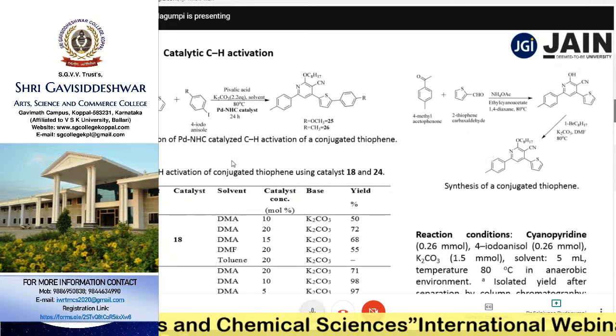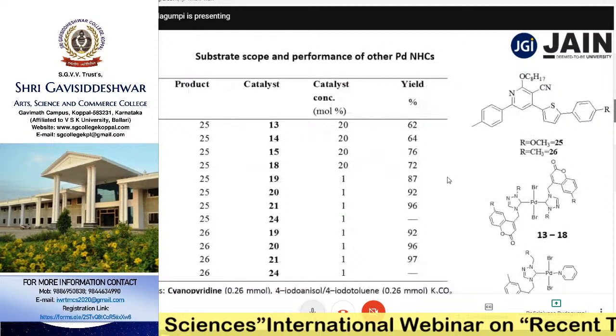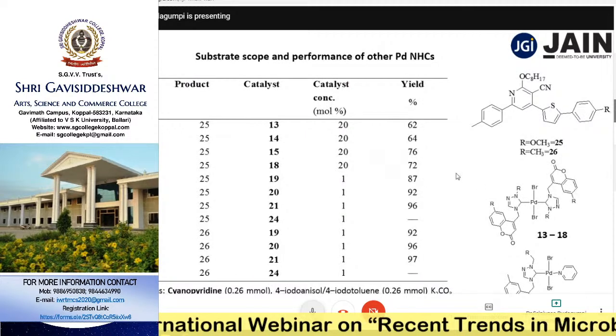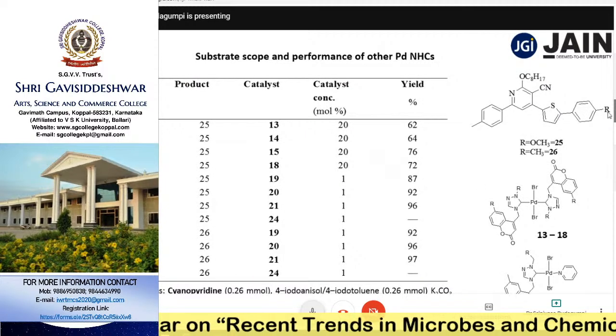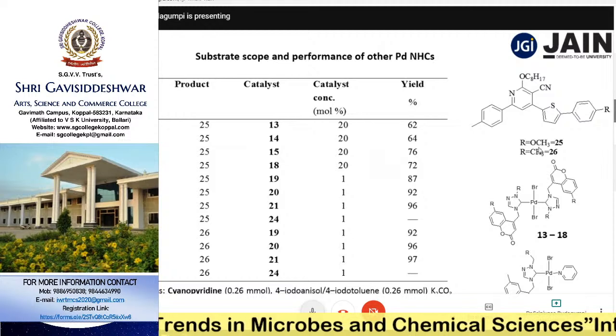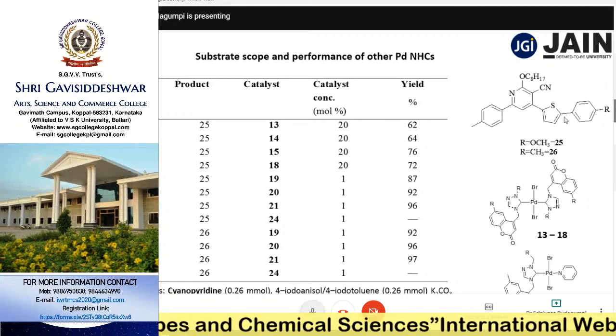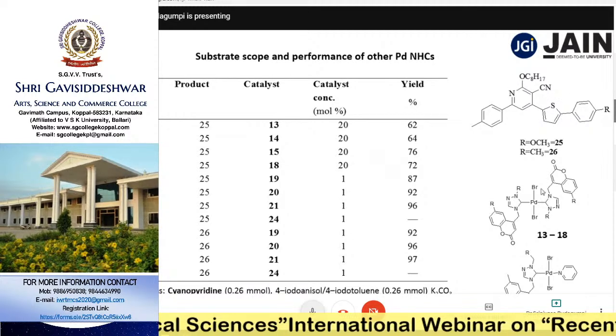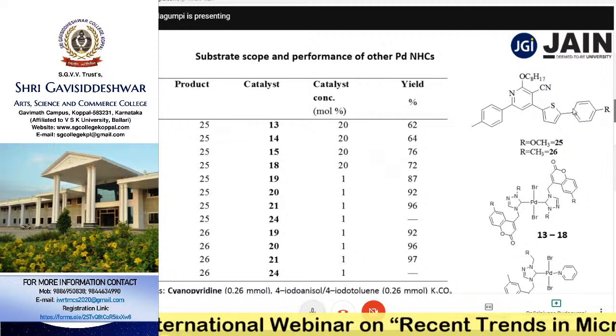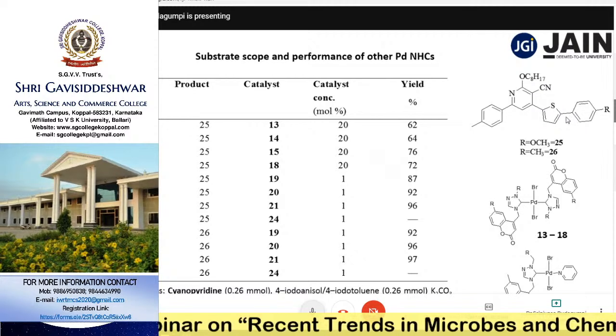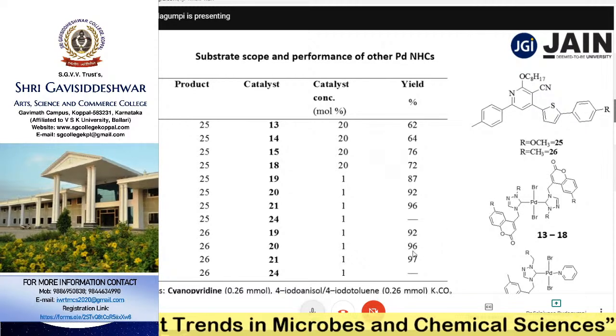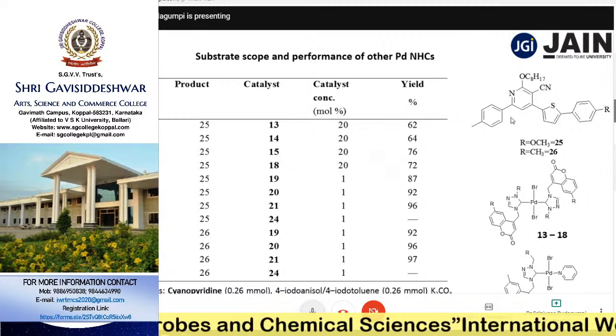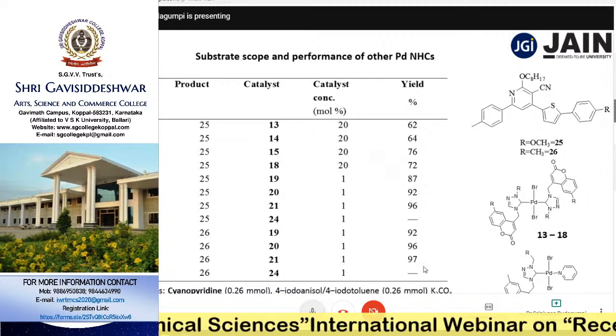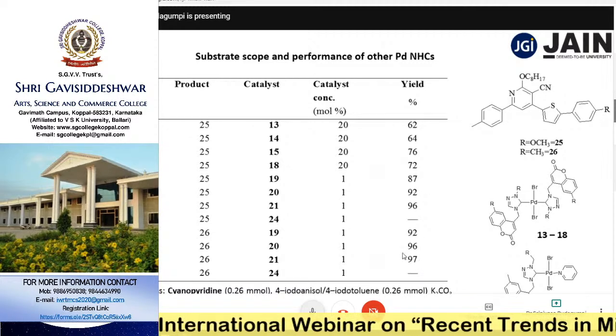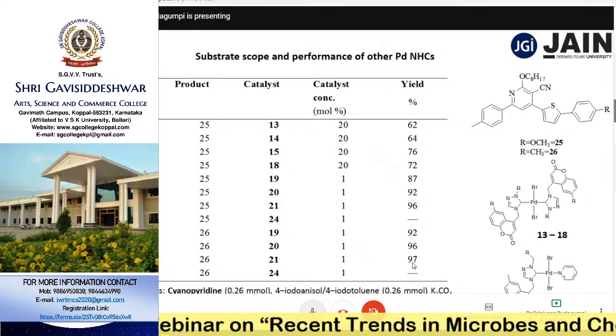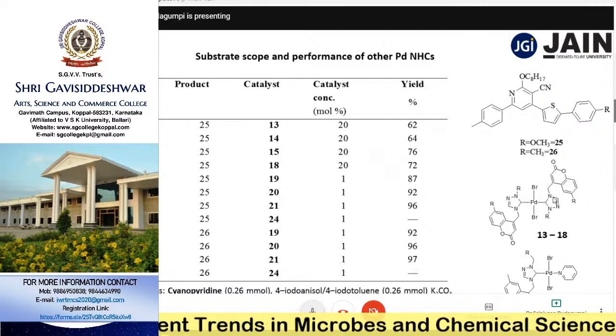And this is the starting material preparation. Now we have studied the substrate scope here. We have changed the R substitution; methoxy is there, methyl substitution is here. So these organic derivatives can be synthesized with the help of these palladium catalyzed direct arylation reactions or C-H activation reactions. We could get the conversion or product formation in the range of 92 to 97%. We got the product isolated in 97% yield with the help of these palladium catalysts.